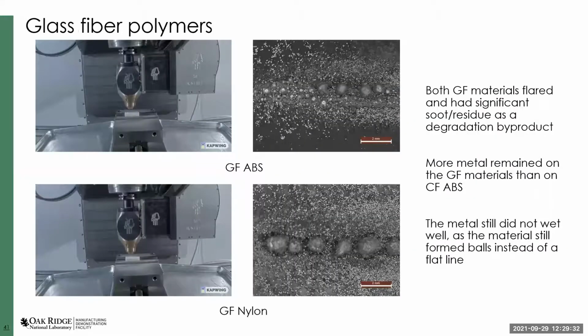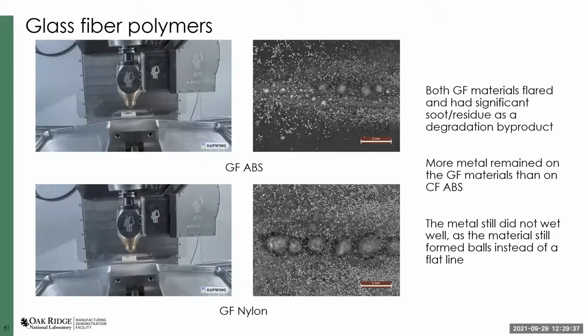So here I'll show the glass fiber polymers. I did an ABS and a nylon, and both of them had more deposition of metal than the carbon fiber ABS because you're working with glass fibers instead of carbon fibers. Both of them still had that flaring from the degradation of the material.